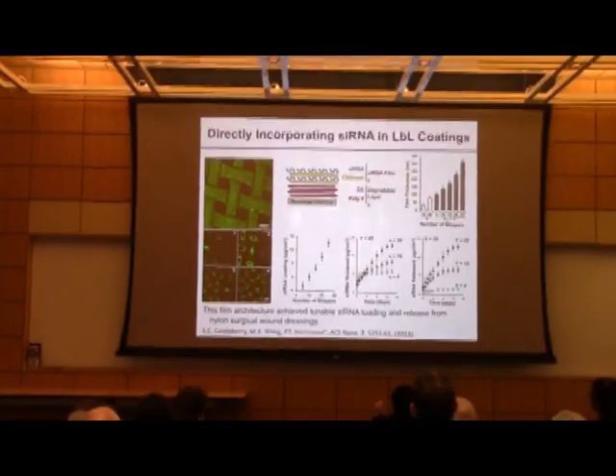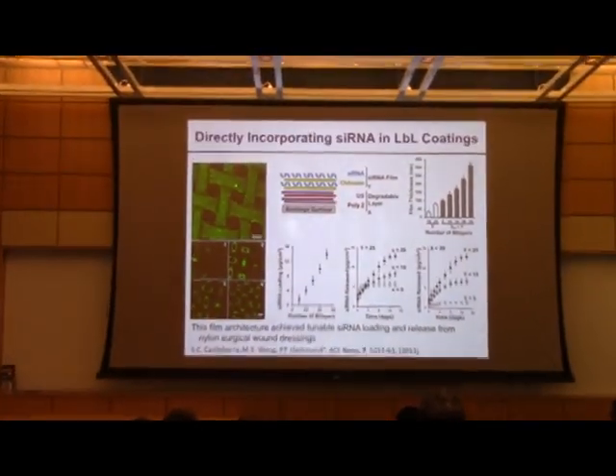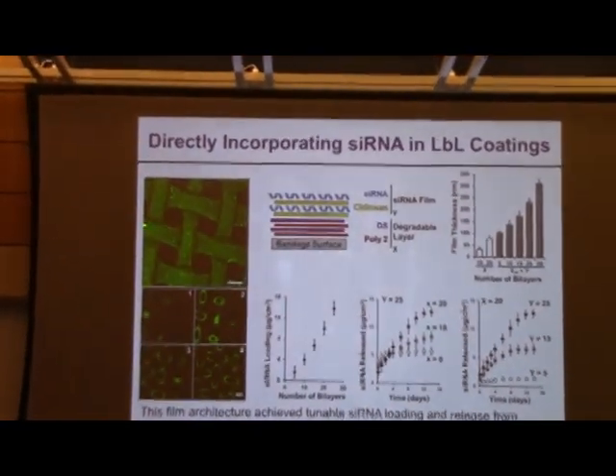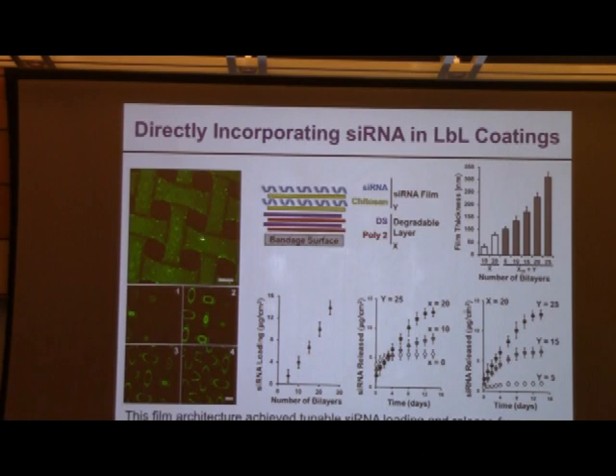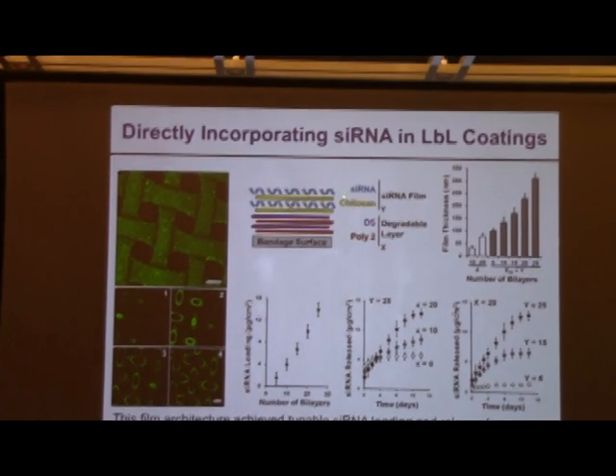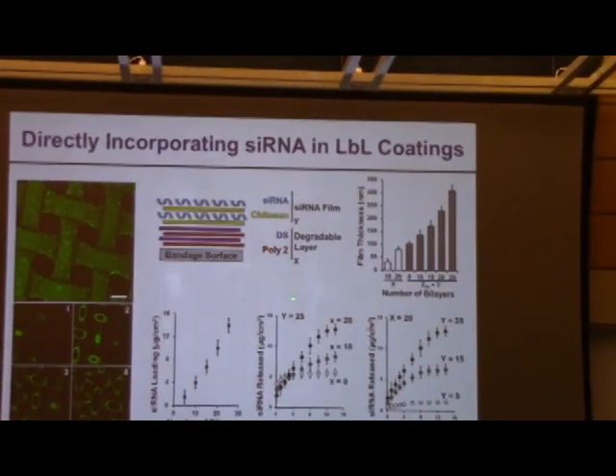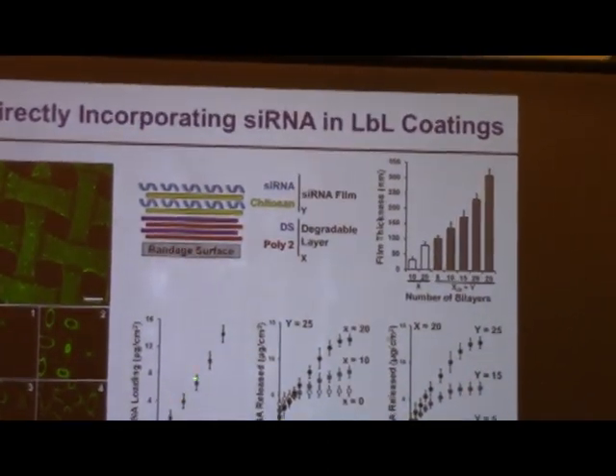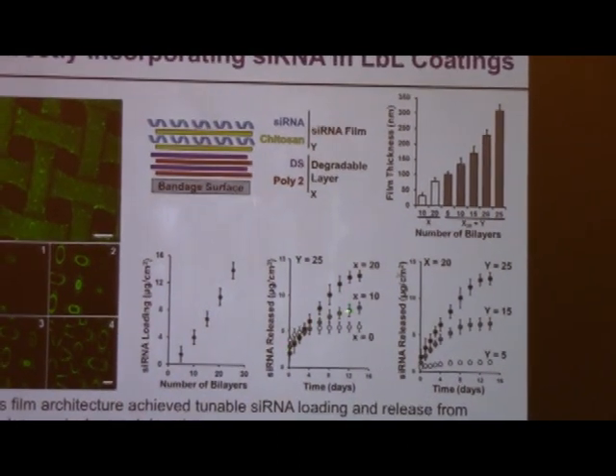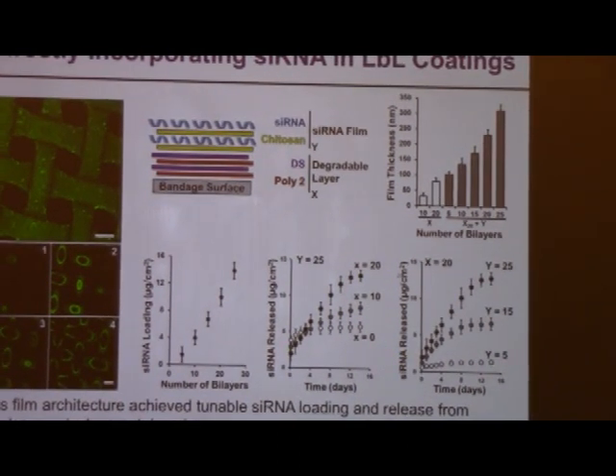This is actually a confocal microscope image of our layered wound dressing. It's nylon Tegaderm, which is used by surgeons, and we coated it with siRNA. siRNA is labeled with a green fluorophore, and so you can see it very nicely. And if you go in and out of the page, as if this is zooming in and out towards you, you can see that it coats all of the different surfaces and crevices of the bandage. We can change the number of underlayers and the number of top layers, and that yields differences in the total loading of the film, as you can see here, and also in the rates of release of the film. So we have a lot of tuning that we can do with these two sets of layers.